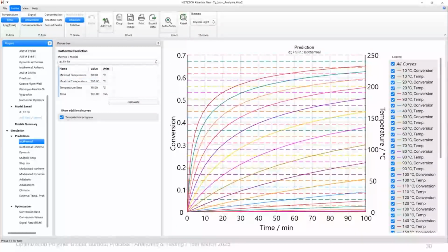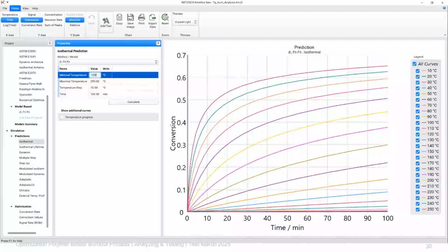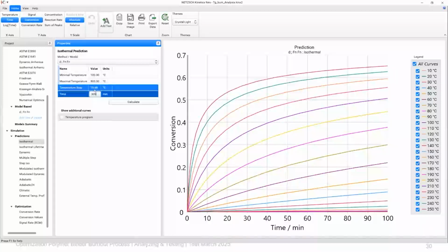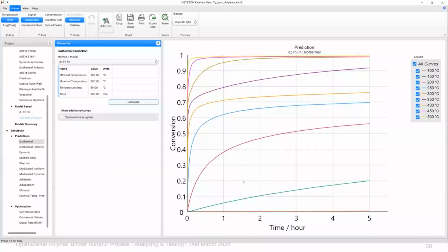For example, here we have the conversion, and here we can do, for example, between 100 and 500, and for 5 hours, which is 300 minutes, and the temperature step I will do 50, and we can calculate. And here you can clearly see that at different isothermals, when we have a constant temperature as shown here, for example for the red one, when we have 200, we can see that after 5 hours we can reach 0.56 as a conversion, and for example at 350 we can reach after 5 hours 0.9.